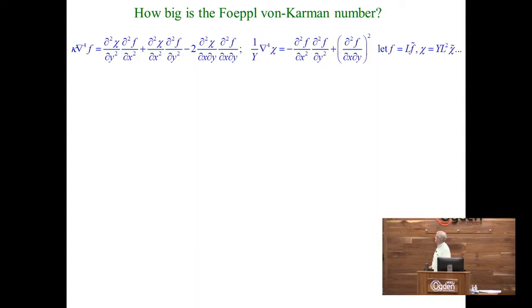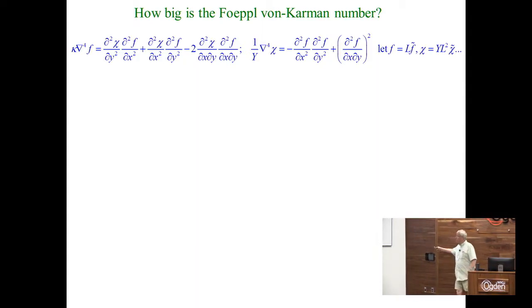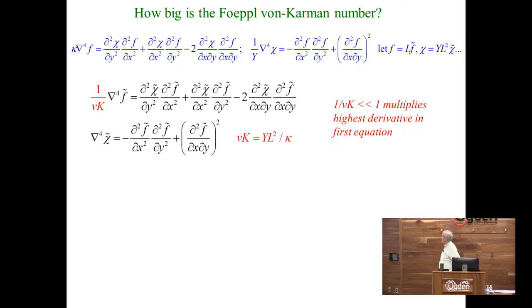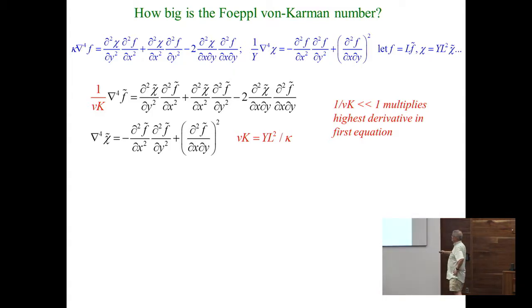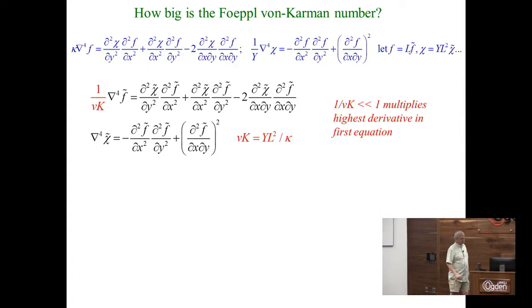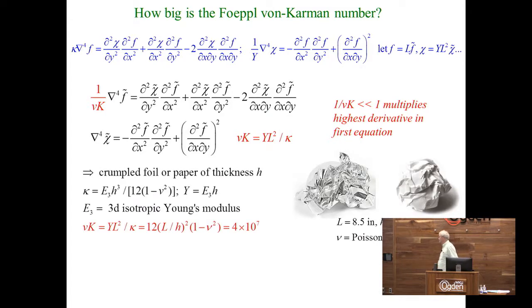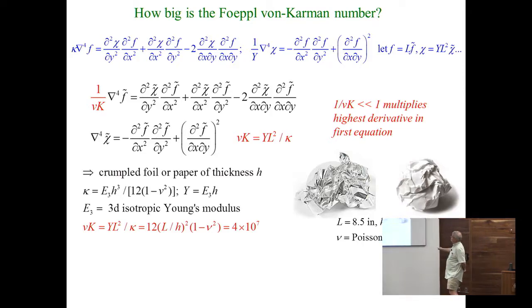So how big is this Föppl-von Kármán number? Here are the equations again. You can rescale as you would in a fluid mechanics problem. And what you find is that this Föppl-von Kármán number, which I'm going to argue is extremely large, appears as a reciprocal in front of the highest derivative in the problem, which is actually in this case the derivative of the F field. And if we work out and see how big this dimensionless coupling constant is, this is all about zero temperature science at the moment, you can take a piece of paper or a piece of crumpled tinfoil, exquisitely textured objects with hierarchical patterns of wrinkling, which, as I said, we still don't understand, even though we throw them in our trash cans almost every day. If you work out what this Föppl-von Kármán number is, you need the 3D Young's modulus of this material. You work it out, it goes like the size of the sheet divided by the thickness squared.